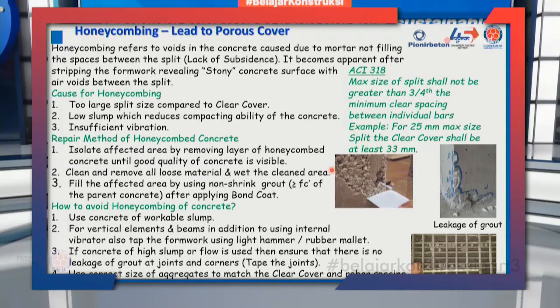Last one is honeycombing. Honeycombing is a defect in the cover. Why does it happen? Because it is not properly vibrated, your slump has dropped, and your choice of aggregate size is wrong. The aggregates are bigger than your spacing. There is an ACI requirement. For example, if 25 mm maximum size aggregate is used, the clear opening has to be at least 33 millimeters.